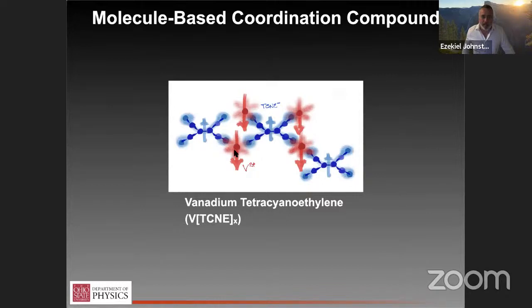So the chemically active piece is a vanadium nitrogen bond here. And the vanadium gives up 2 electrons going to the 2+ state. That then reduces 2 TCNE to the TCNE minus, and we get ferromagnetic order with a large spin on the vanadium site anti-parallel to a small spin on the TCNE site.